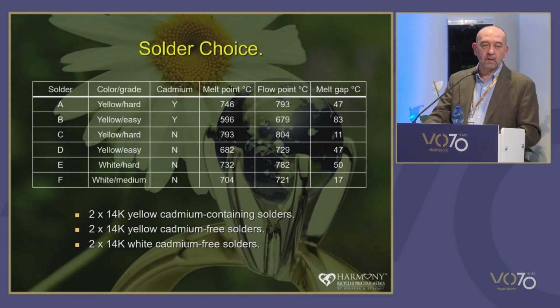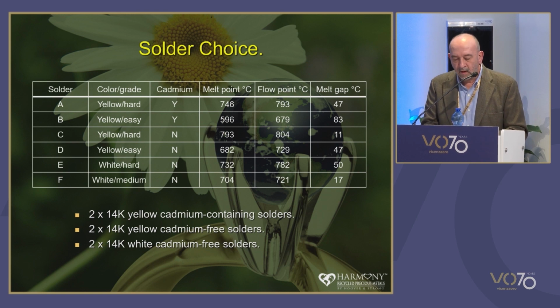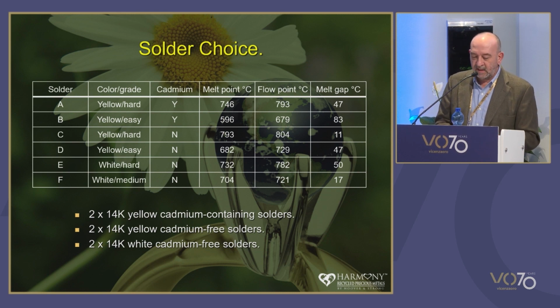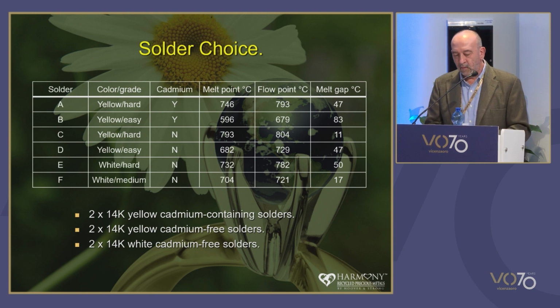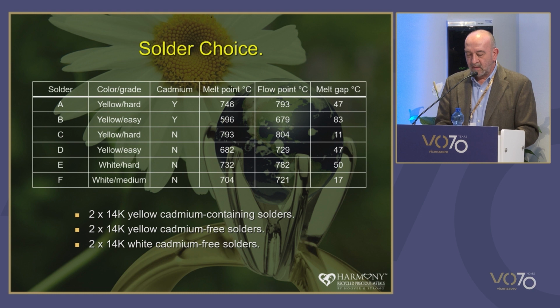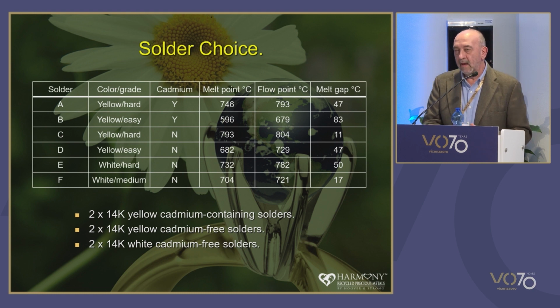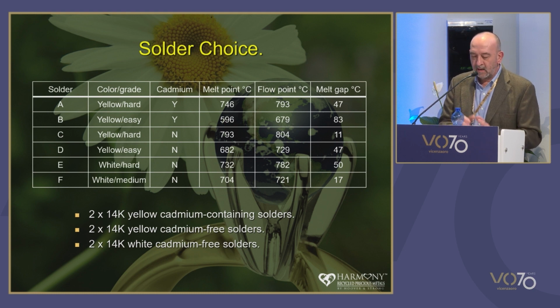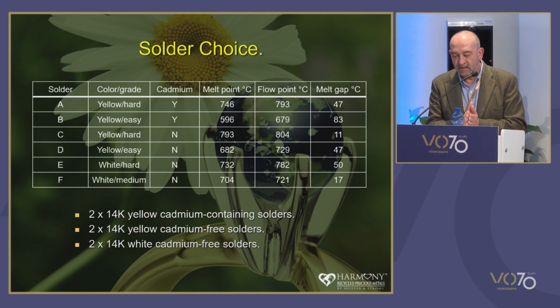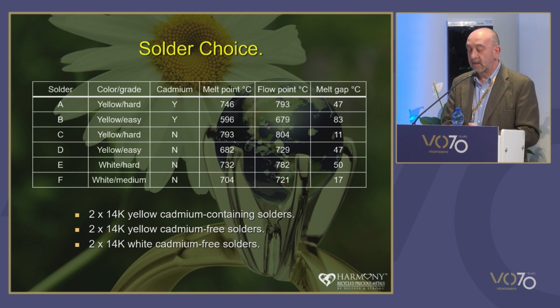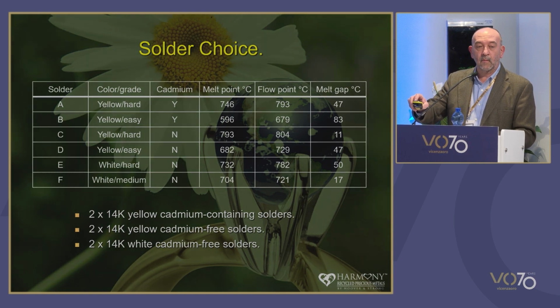So we chose a relatively simple study. We did two 14 yellow cadmium-containing solders, two 14 yellow cadmium-free solders, and two white cadmium-free solders. And again, as you can see from these melt gaps, the cadmium-free versions do have narrower melting gaps than the equivalent cadmium-containing solders. So the type of test we're going to look at, we came up with.